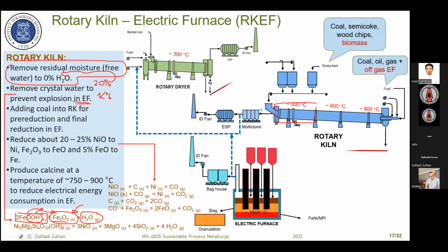For saprolite ore, the minerals are garnierite, or it could be antigorite or serpentine. There is also crystal water in the mineral at temperatures roughly around 600 to 700 degrees. We can dissociate it and remove the crystal water. You can see here, we can make it free from the crystal water. We can also dissociate the nickel in this mineral into nickel oxide, and Mg into MgO and SiO2.